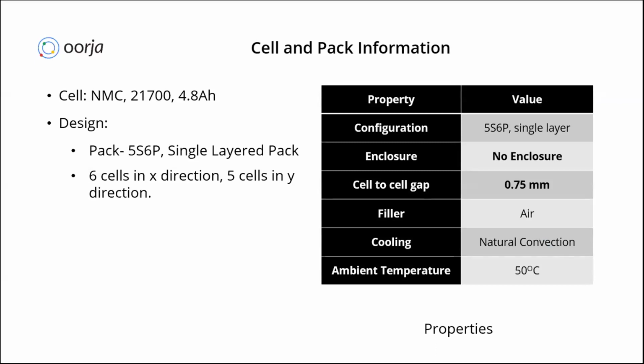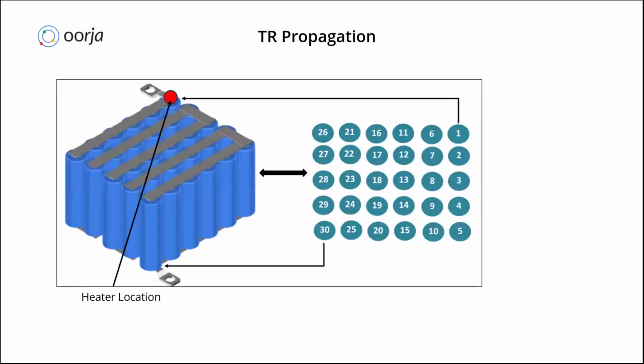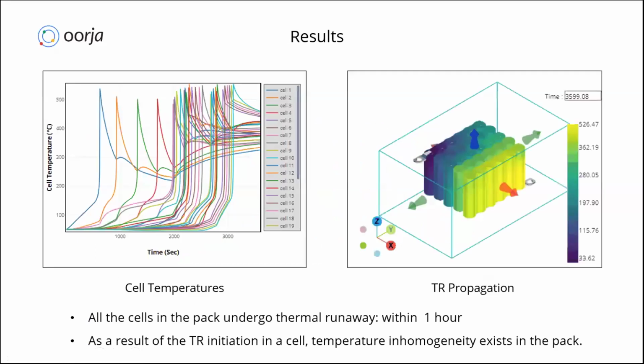Now, the same pack we modified for two cases. One was if we are using the pack with cell to cell gap as 0.75 mm without any enclosure. And if this cell is considered as a defective cell, in that case, we wrapped a heater around that particular cell and then took that particular cell into thermal runaway. The objective of this study is to understand that if this cell is going into thermal runaway, whether the rest of the neighboring cells are also going to get into thermal runaway or not, whether the initiation happens or not. And because of that, whether the entire pack also gets into thermal runaway or not, that propagation also happens or not.